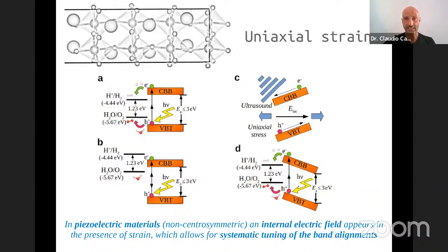And the second one is that, of course, this internal electric field also enhances the recombination time of the excitons that you form when the material absorbs these light photons, right? So essentially, a photon comes here, so you create this electron-hole pair, right? Typically, this electron recombines after some short time, so you no longer get this separation of charges, right? This is not good. So you would like to have these two charges separated as long as possible in order to be able to drive these two reactions as efficiently as possible.